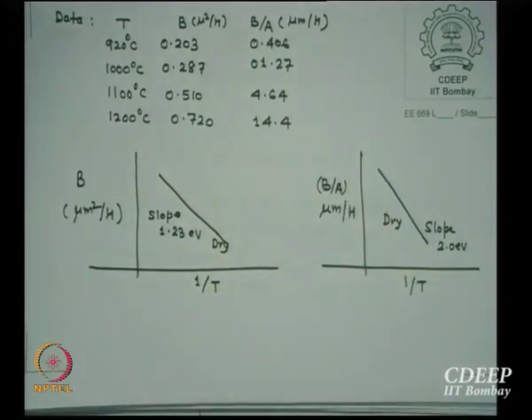This is experimental, because I actually went and did oxidation, monitored the thicknesses at different temperatures for different times and plotted them to get B and B by A at different temperatures. So this is no model. This is essentially what I can measure. And now I want to prove that what I said in a model probably fits what I monitored, and therefore the Deal-Grove model is reasonably good. Is that point clear to you?